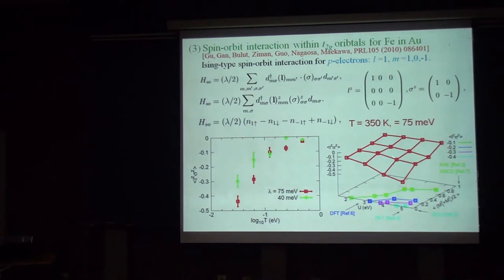Here, let me try to explain this complicated diagram. If you do not include on-site Coulomb interaction. And this spin-orbit coupling parameter is very small. That means you will not observe spin Hall. But you gradually increase on-site Coulomb interaction, which you can do computer experiment for that. You can see that this parameter increases dramatically. When you have on-site Coulomb equal to 5 eV, that's what I used before in the band structure calculation. But you can also imagine that you can apply magnetic field, which then can induce magnetic moment to the system. But the moment was screened when Kondo takes place. And, but when you increase this induced spin magnetic moment, this parameter decreases eventually to zero.